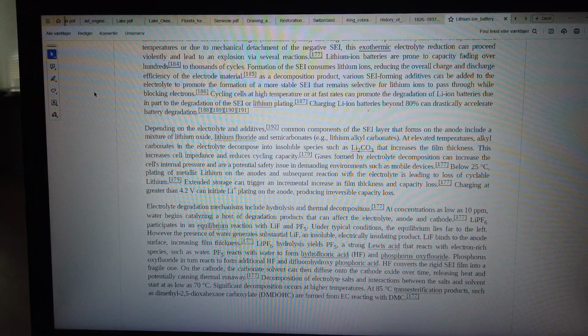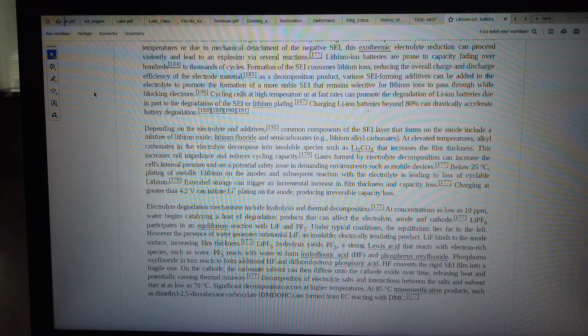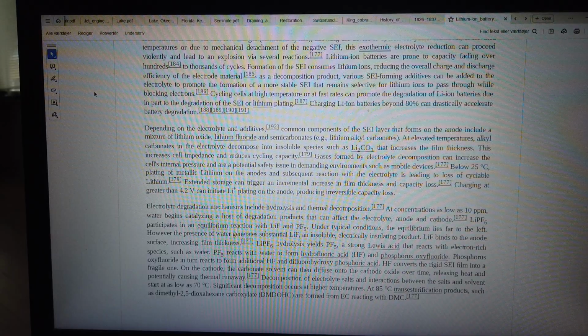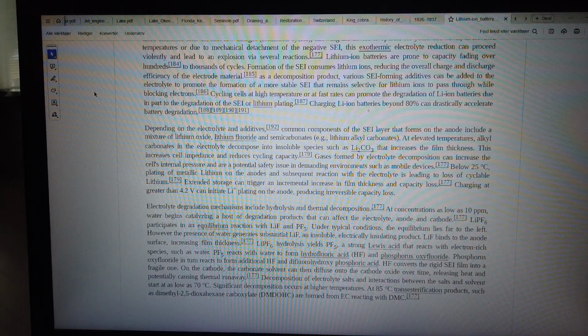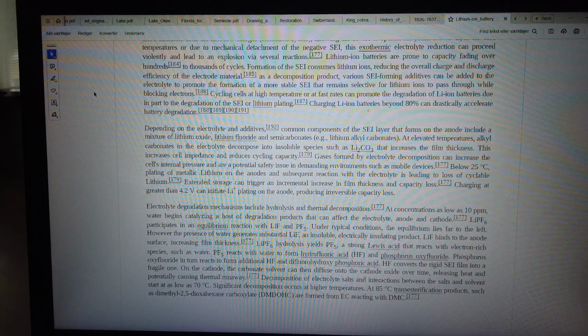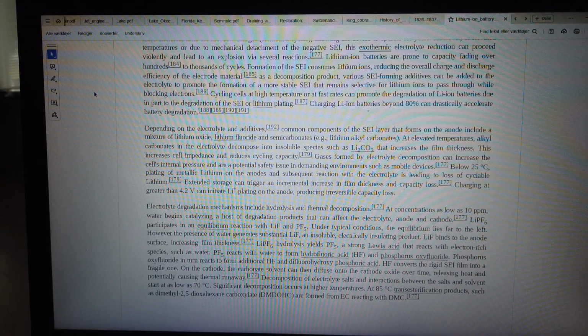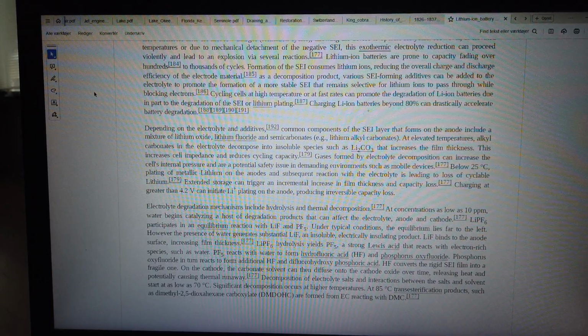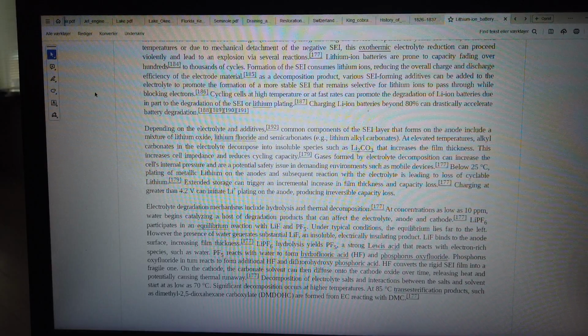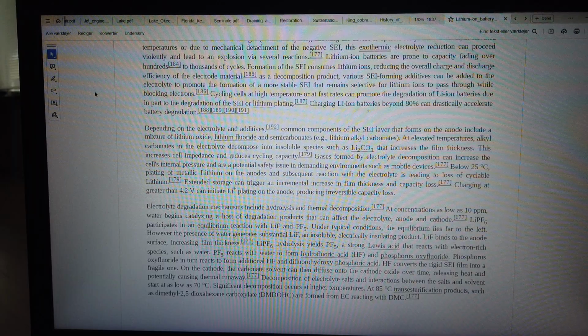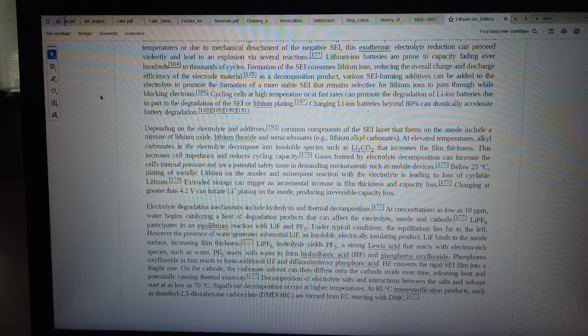LiPF6 hydrolysis yields PF5, a strong Lewis acid that reacts with electron-rich species, such as water. PF5 reacts with water to form hydrofluoric acid, HF, and phosphorus oxyfluoride. Phosphorus oxyfluoride in turn reacts to form additional HF and difluorohydroxyphosphoric acid. HF converts the rigid SEI film into a fragile one. On the cathode, the carbonate solvent can then diffuse onto the cathode oxide over time, releasing heat and potentially causing thermal runaway.